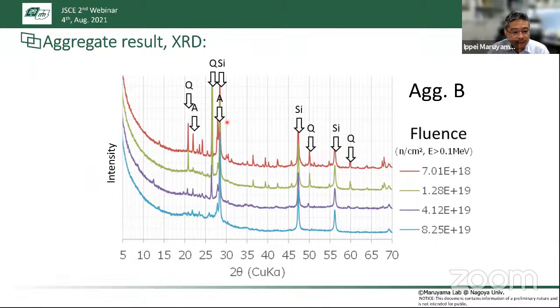This is the result of the X-ray diffraction pattern of aggregate B, the sandstone, with different neutron fluence levels. Red is the lower neutron fluence level, and blue is the higher neutron fluence level. We confirm the quartz peak, the peak belonging to Q, and the albite peak here and here. We can confirm that the peak shifts to a lower 2 theta angle, which indicates that the structure expanded under the neutron irradiation. Also the peaks become weak after the neutron irradiation, and some disappeared, which proves that the crystal structure is destroyed after the neutron irradiation.